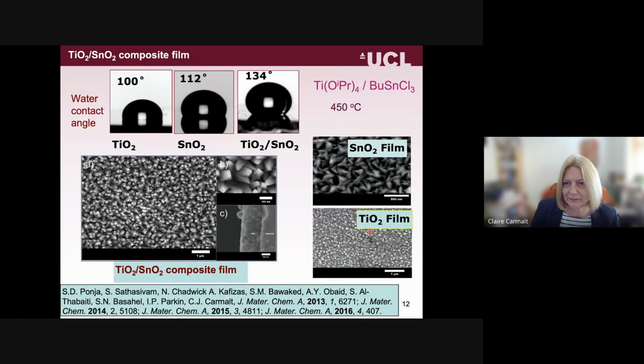Now you can do depositions of hydrophobic species, and instead of using polymers, you can use alkoxides and so on, or metal oxides. And so we had a look at this. Well, we'd done this a number of years ago, where we made this titanium dioxide, tin dioxide composite film. So you can take titanium isopropoxide in ethyl acetate on its own, and you deposit TiO2, and you can see the water contact angle was 100 degrees for that, and that's the morphology. You can take butyl tin trichloride, also in ethyl acetate, and form tin dioxide, similar, with a slightly higher hydrophobic contact angle.